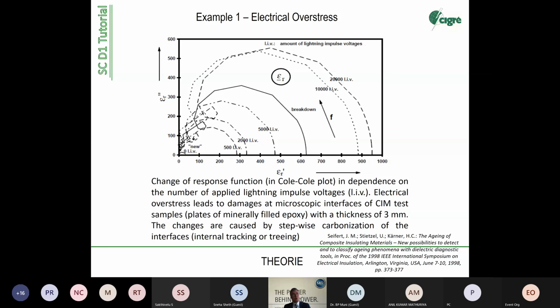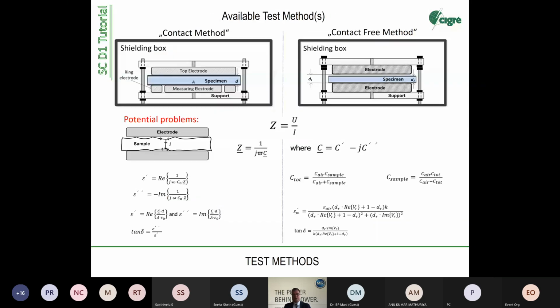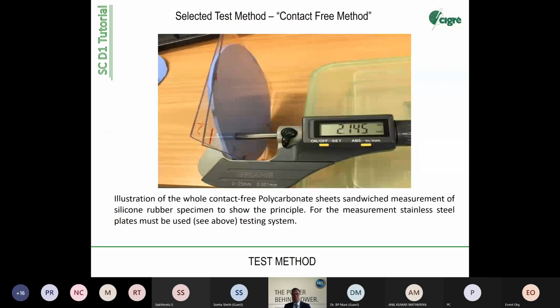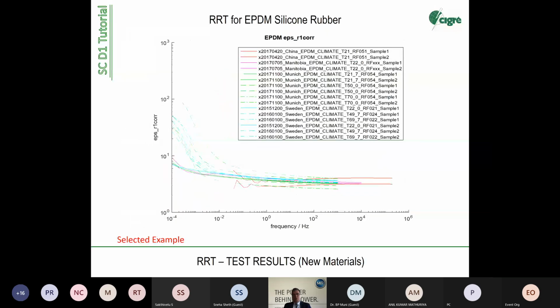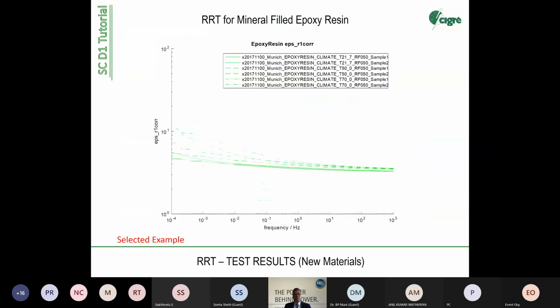You can load the material and it will not show any kind of aging until you exceed the so-called damage limit. Damage limit theory also applies for materials. If you always stay underneath the damage limit, so the voltage stress or the water stress is lower than the damage limit, you don't see any aging. Same here. That's the curve we have to look at, and the round robin test. You see, this is a good quality material because you have not a very strong response. So the response is relatively flat.